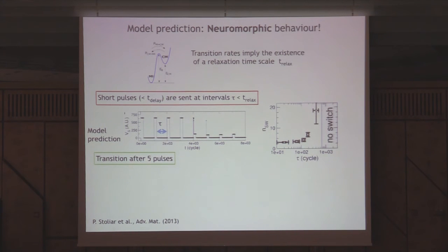Now when you wait, there are two possibilities. You wait beyond that relaxation time or beneath that relaxation time. If you wait too long, of course the system will fall back. If it falls back, then you will not be able to, with another short pulse, get the system to have the transition. So you can apply as many pulses as you want, but if they are too far apart one from the other, the system will not have a transition.